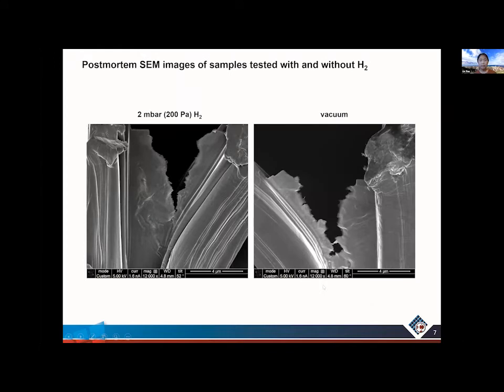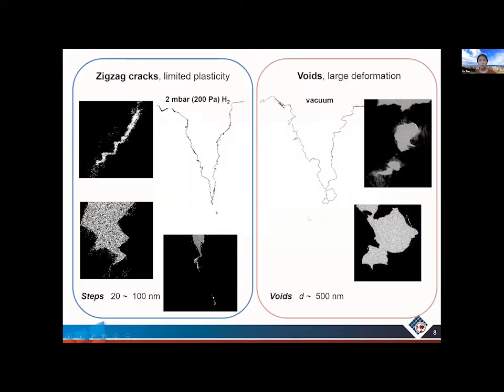We can then check the post-mortem SEM images of the sample, but at first impression, you don't really see much of a difference. So I think this part also emphasizes the importance of taking the in situ experiment to see how the crack really nucleates.